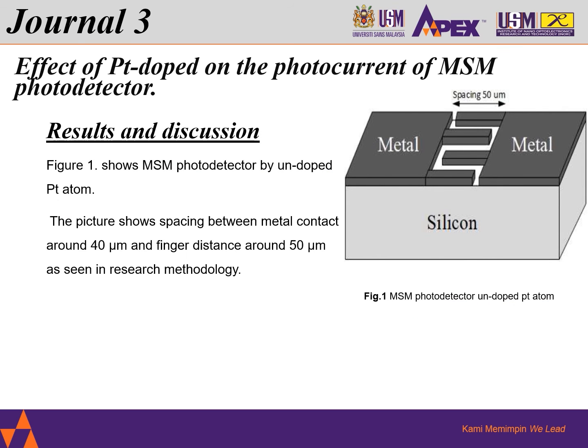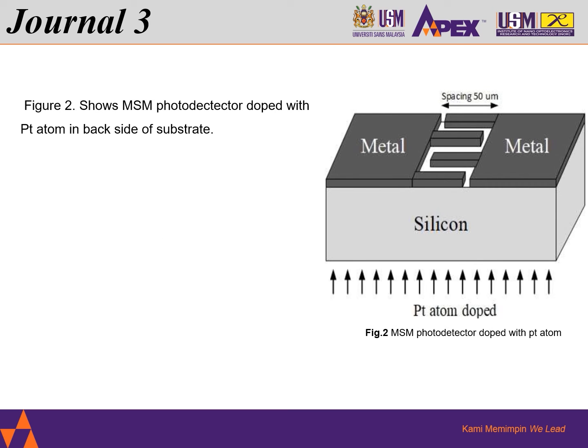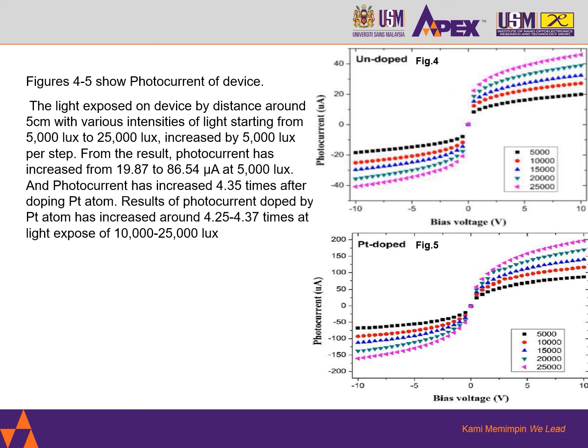Result and discussion. Figure 1 shows MSM photodetector undoped Pt atom. The picture shows spacing between metal contact around 40 micrometer and finger distance around 50 micrometer, as seen in research methodology. Figure 2 shows MSM photodetector doped with Pt atom in backside of substrate. And figures 4 and 5 show photocurrent of device.